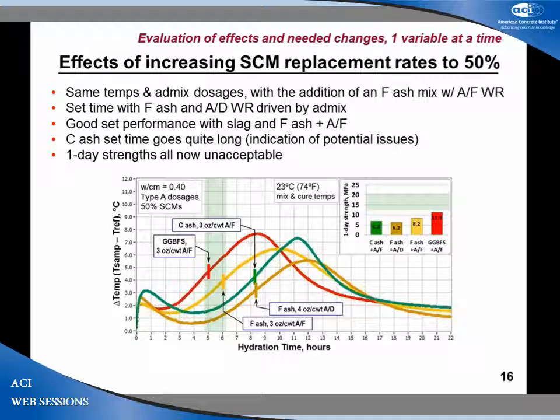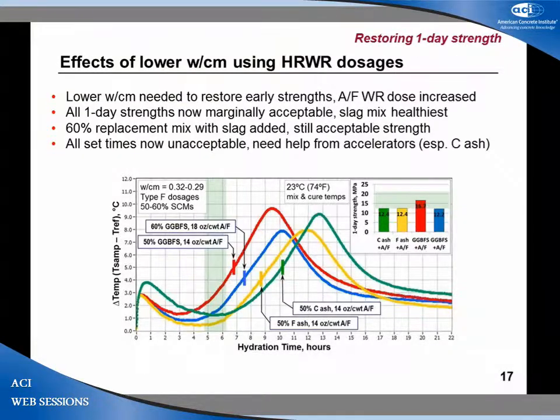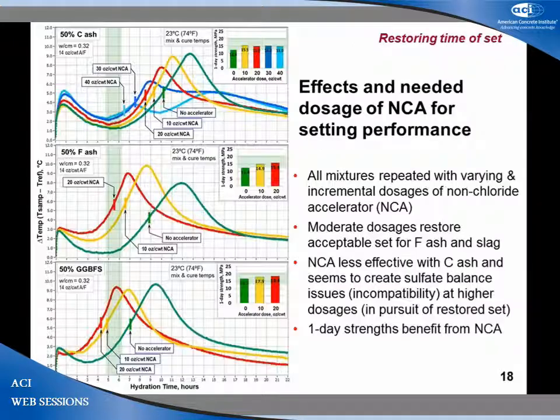So what we want to do is to recapture the one-day strengths, probably is the next step in this process. We do that by lowering the water cementitious ratio, the use of high-range water reducers, and whatever it takes to get just into the entry level of our target band. Now we are seeing some additional retardation from the effects of those chemical admixtures. It's true in almost every case when you're using water reducers. So now we have to accelerate the setting time to get it back to more replicate mixtures. And as we put in a non-chloride accelerator, very similar to the corrosion inhibitor that was being used in the previous presentation, we're successful in restoring our set times back into the target band in many cases, except in the case of the C ash, which is the problem actor.